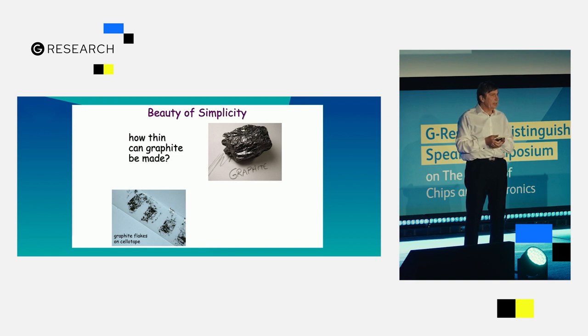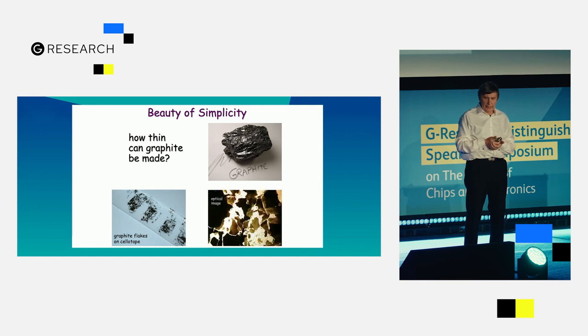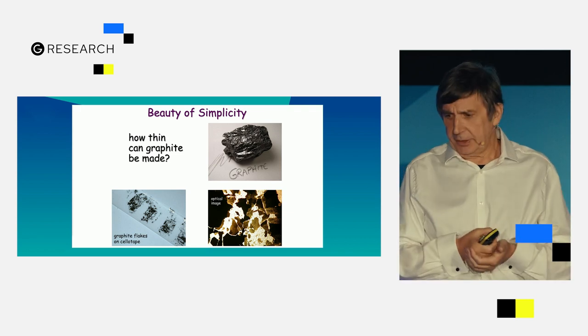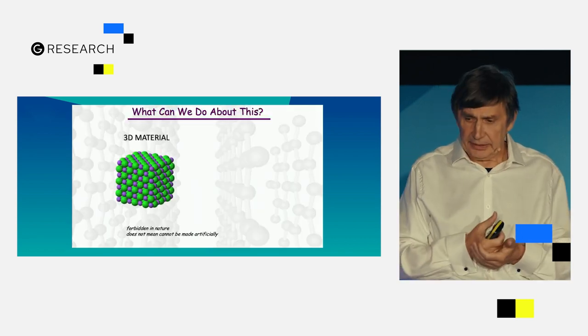If you look at the microscope, light shines from the back and you see rubbish on the surface. Some pieces of graphite in optical image are dark, it's thick, it's essentially metal, light doesn't go through. But some pieces are transparent and it immediately tells you that those pieces are extremely thin. The thinnest one here probably a couple of nanometers thick. No one has before us made those thin pieces of graphite. It was kind of a Eureka moment. We got thin pieces of graphite. Very happy with that.